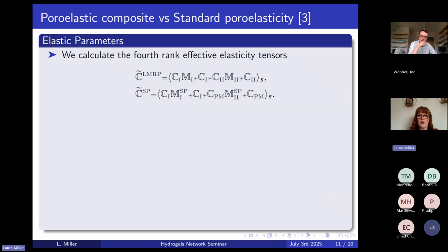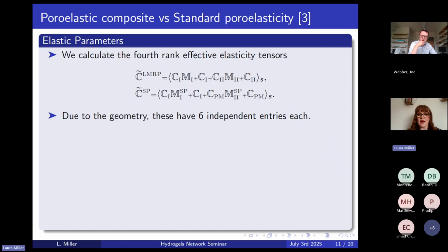Okay, so just to, again, put these tensors a little bit bigger so you can see them more clearly. So this is our two fourth rank effective elasticity tensors. This first one from my model, this second one from the next best case that we could come up with. So these are going to have 6 independent entries due to the geometries we chose. So the geometries, as I showed you on the last slide, were cubes with various cylinders. So that was why we just have the 6 independent values.